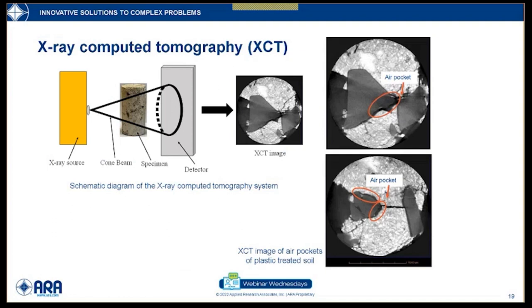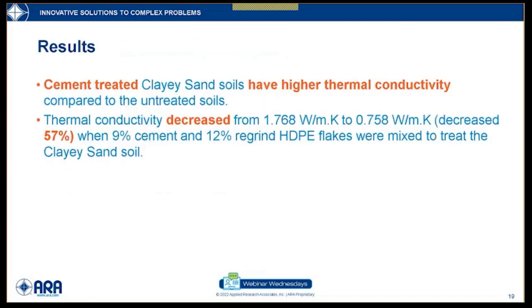The low thermal conductivity of the soil sample when it's mixed with recycled plastics was also proved by X-ray computed tomography tests. The images show that there are air pockets in between the waste plastic and the soil matrix. And air has a very low thermal conductivity. It cannot conduct heat, and thus it leads to the low thermal conductivity of the plastic mixed soil samples. The result of this thermal conductivity test is that the cement-treated soils have higher thermal conductivity than the untreated soil, and the thermal conductivity decreases up to 57% when recycled plastics and cements are mixed in.